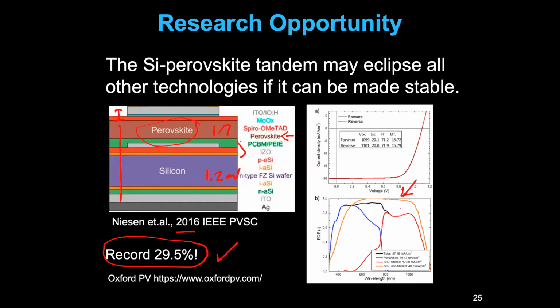I usually use the perovskite with the bandgap of 1.5 eV. So we can make the smaller bandgap perovskite. The bandgap is 1.2 or 1.3 eV. So we put these two different bandgap materials to make a tandem solar cell architecture. I think the silicon part is not flexible and very thick. So if we can make perovskite tandem architecture, we can get a flexible, high efficiency, and very thin tandem solar cell, all perovskite solar cells.